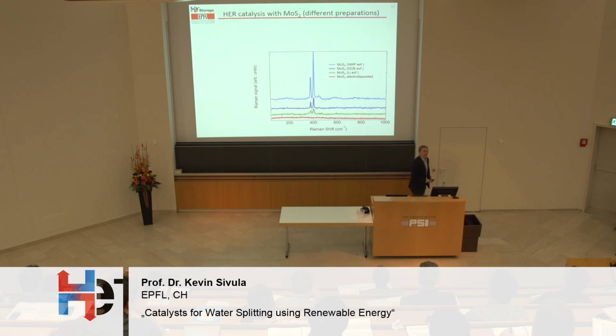And to get an insight into that, we did some analysis using Raman spectroscopy. And if you don't know what Raman is, I can tell you very quickly that it's a way to measure essentially forbidden phonon modes in a crystal material. And the signal that you observe from your sample is correlated somehow to the quality of that crystal, defects, certainly the crystal phase that you observe. We noticed something striking about the crystallinity, the Raman response for these materials as a function of the processing technique. While our NMP exfoliated material gave a very strong signal suggesting it's quite crystalline, that diminished as we moved to dichlorobenzene or the lithium. Finally, for the electrodeposited material, absolutely no Raman peak was observed at all.